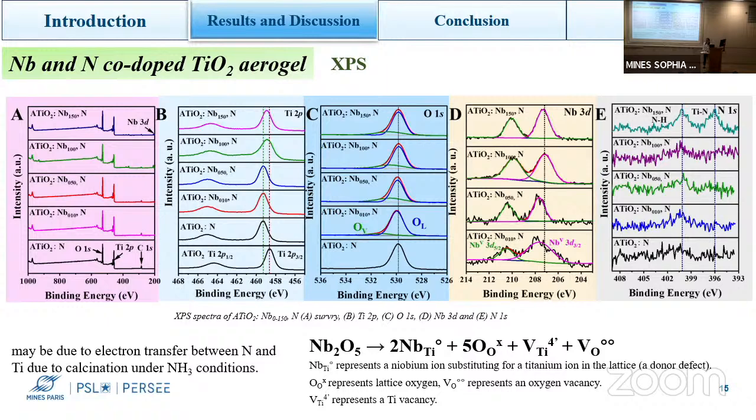Do you think this could also be due to the nitric acid you added? In acidic medium, you can increase the surface charge because of some protonation of the oxygen group at the surface. Could it be an effect of repulsion between particles, for example, to help make the gel? To make a gel we need hydrolysis and condensation, but it is too fast.